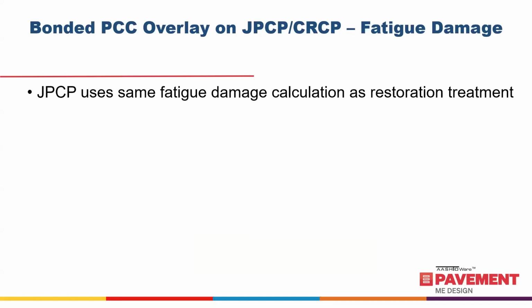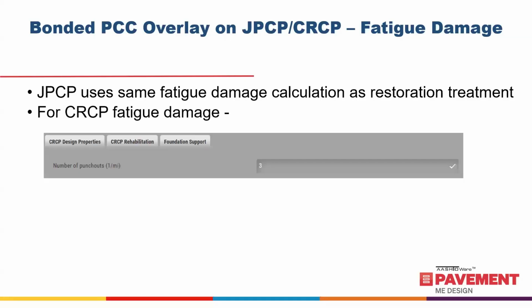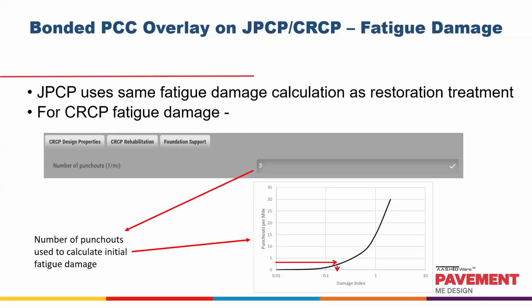As far as the fatigue damage, you're using the same fatigue damage calculations as restoration. For CRCP, you're not doing a difference between before and after slabs. You're basically assessing it from the number of punch outs, and this is actually the correct graph. So I apologize about the previous one, but this is the punch outs per mile versus damage index. So in this particular example, we have, I'm sorry, three punch outs per mile, and you relate that to the damage index, and that's going to be your starting point. So in the analysis, your existing concrete is at that fatigue level, and then the fatigue damage that accumulates after that point is basically going to be assessed from that starting point.